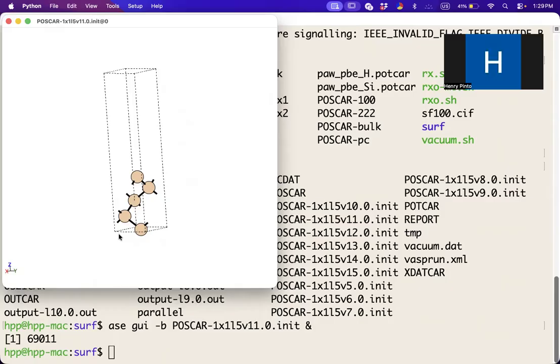After that, we're going to see the relaxation. So the first step is describing an analysis. First of all, I'm going to teach you how to passivate this, how to add two hydrogen atoms here. And then we are going to proceed with two relaxations, right? In the first relaxation, we fix everything, including this last silicon, and we allow the hydrogen to find its equilibrium position, right?